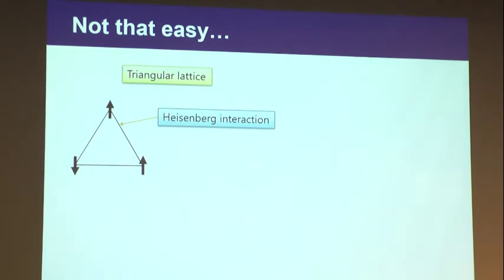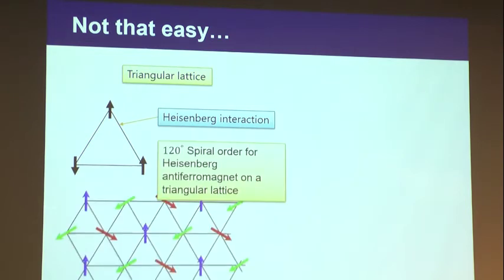It turns out that it's not that simple to find quantum spin liquid this way, because most magnetic interactions are so-called Heisenberg interactions rather than Ising interactions. In other words, the spins can point in any direction rather than just up and down like in an Ising spin. If you allow that on a triangular lattice, you can find a unique ground state where the spins rotate by 120 degrees, forming a three-sublattice magnetic ordering, the so-called spiral order for a Heisenberg antiferromagnet on a triangular lattice. So that's not a quantum spin liquid.